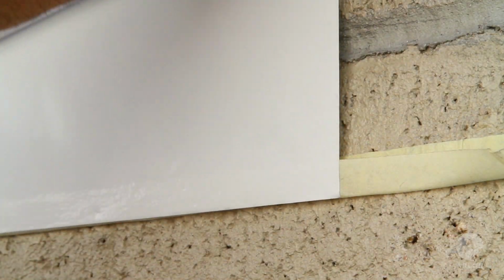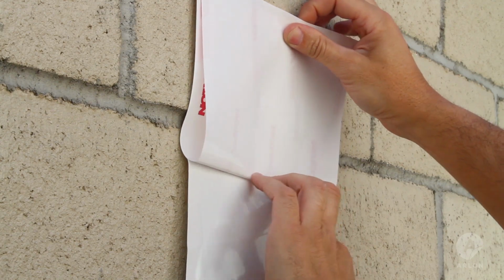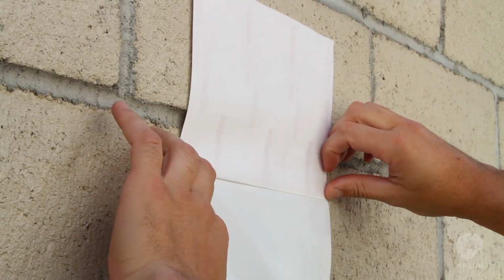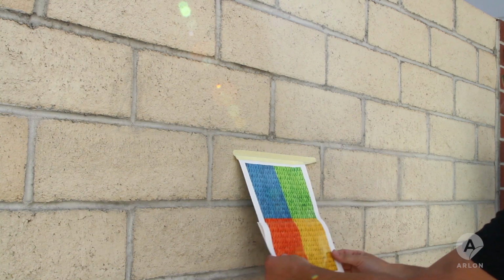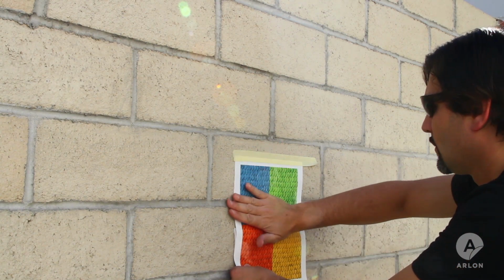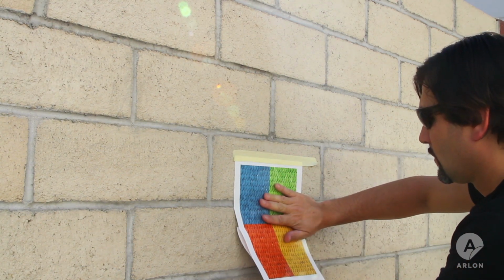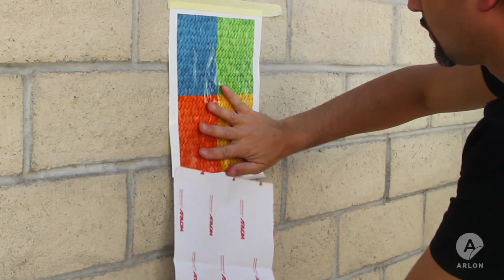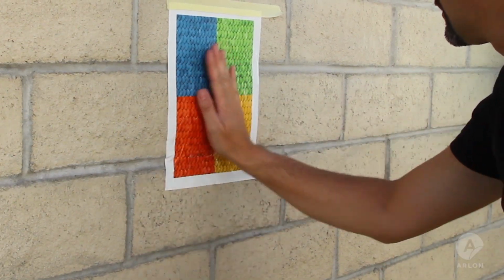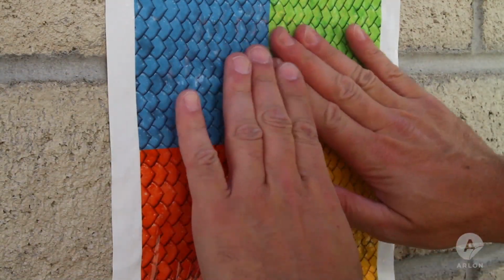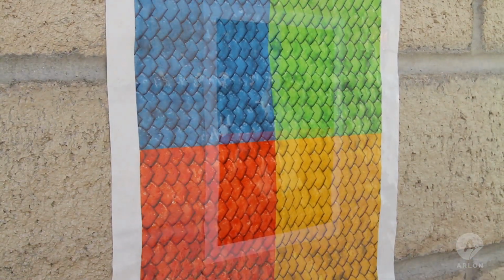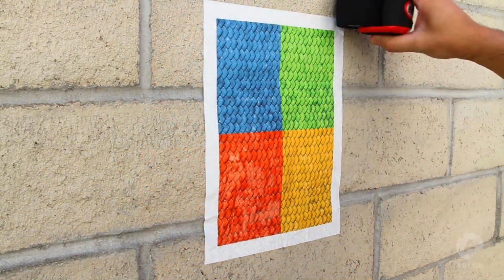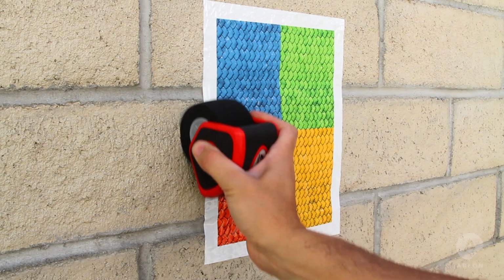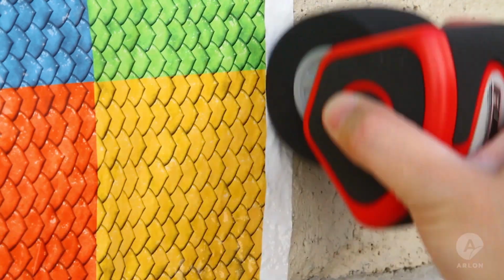Begin by peeling the liner halfway. Many wall products have exceptionally tacky adhesives, so removing all of the liner at once can make the test much more difficult. Smooth the vinyl out with your hands, making contact with only the high points of the texture. Use a roller to secure the edges before using heat. Unsecured edges will immediately shrink when heat is added.